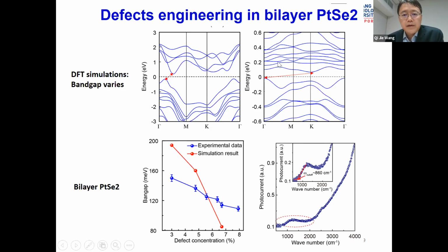And we found out that in the right figure, with only a few percent of defects, in fact, the band structure can be dramatically changed with a much narrower bandgap, corresponding to 0.1 eV. This provides us the opportunity that through defect engineering, we can engineer the bandgap of such material in order to cover a wider mid-infrared region. And this absorption spectrum shows indeed the cutoff wavelengths can reach 11 or 12 micrometers. That's the reason why we still see a good response at the 10 micrometer excitation.